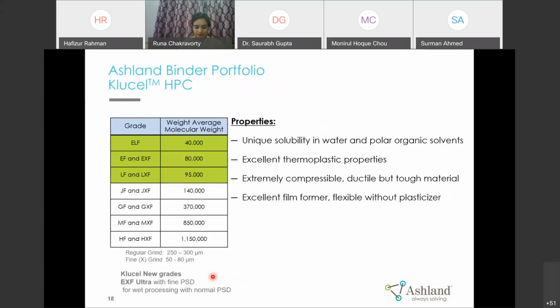Then coming to Klucel, hydroxypropyl cellulose. This is a very good binder. It comes with different grades which vary in their molecular weight. Out of all these grades, lower molecular weight grades like EF and LF are highly recommended as binders. ELF is mainly used for coatings, and high molecular weight grades from JF to HF are used for extended release formulation or hydroalcoholic gel formulation. As it is soluble both in water as well as in organic solvents, these grades can be used for aqueous as well as hydroalcoholic gels.